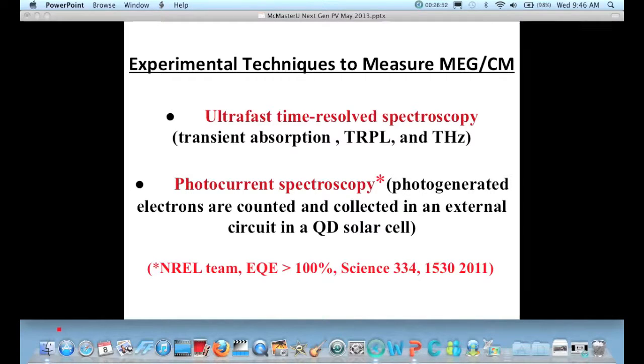Or you can use photoluminescence or terahertz spectroscopy. There are various ways to pump and then probe using spectroscopy to determine how many electron-hole pairs you have. This is indirect because you're looking at how the population affects light. So you're not counting the electrons like you do when you measure the current. If you measure the current, you actually count the electrons. And that's the most direct.